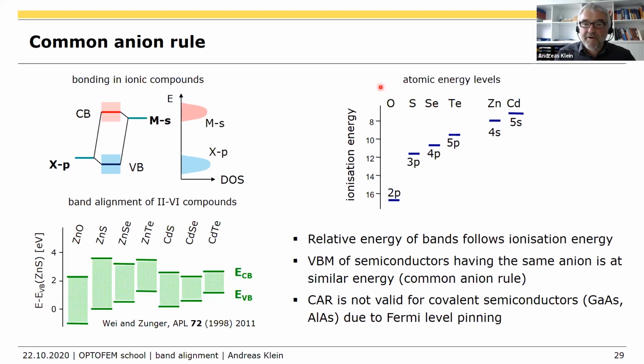And now you can look at, for example, what are these energy levels for the chalcogenides: oxygen, sulfur, selenium, and tellurium. These are the p levels. And you see that they go down in energy. And now look at the valence band alignment of these two materials. This is a calculated one, but experimentally we reproduce that very nicely. So this is cadmium telluride and zinc telluride. First of all, you see the two have really very similar energies. Also, the two selenides, zinc and cadmium selenide, have very similar valence band maxima. Cadmium sulfide and zinc sulfide have very similar valence band maxima. And you see also the tellurides, selenides, and sulfides go down in energy just like this. So that seems to be a principle. This is a very simple rule. Yeah.